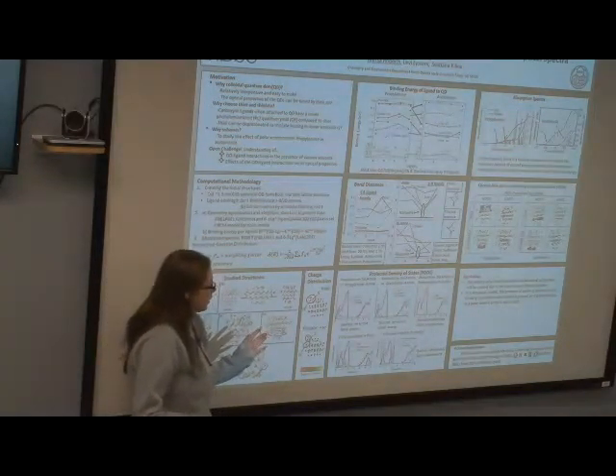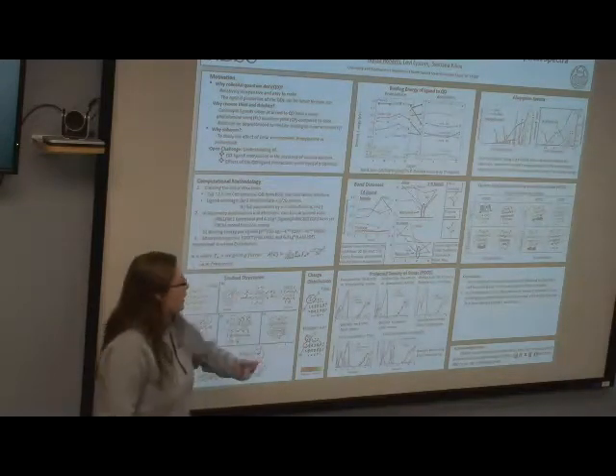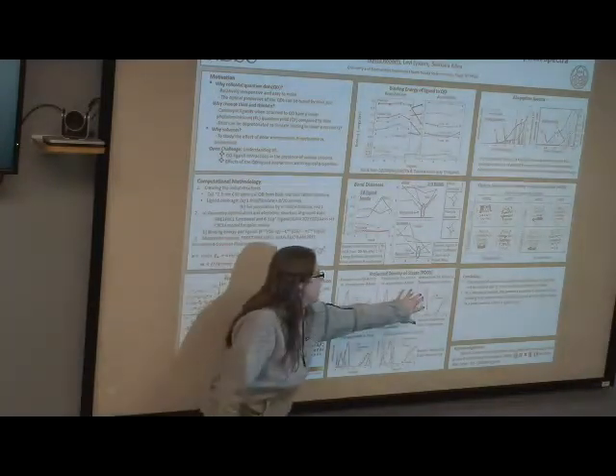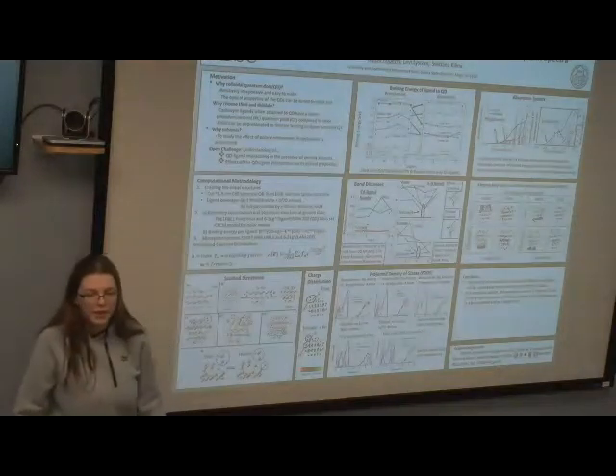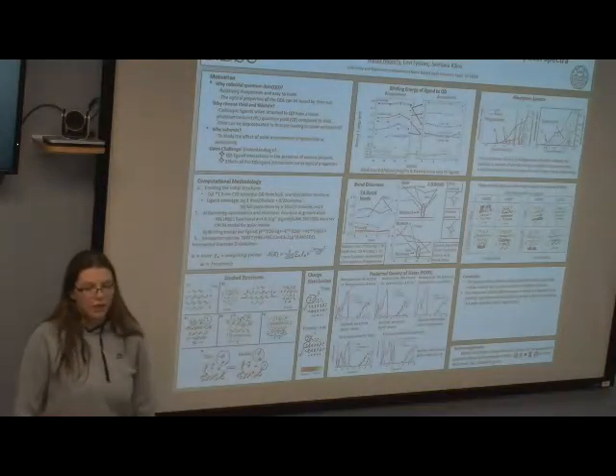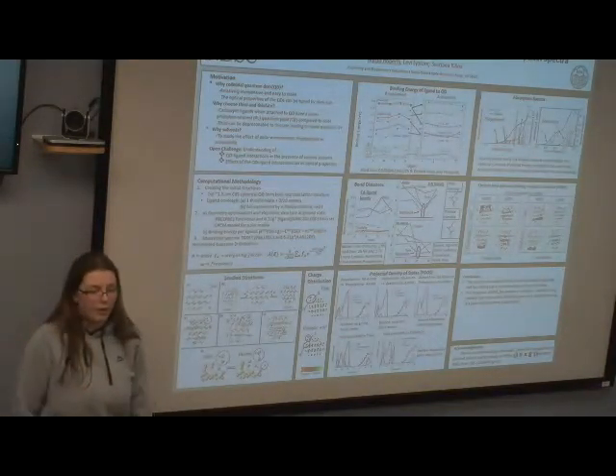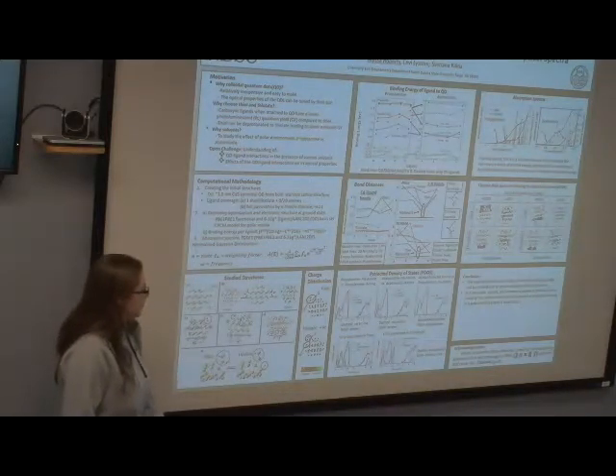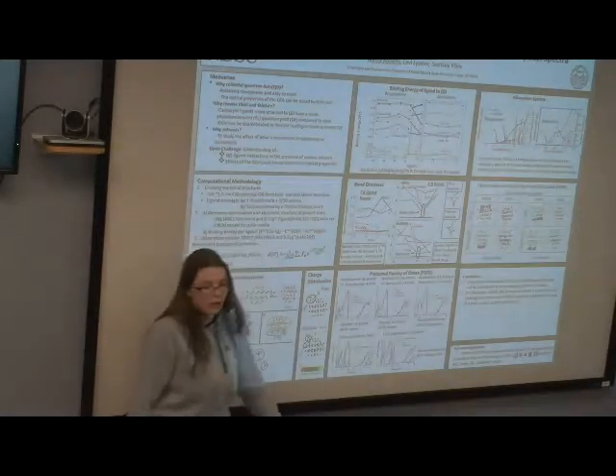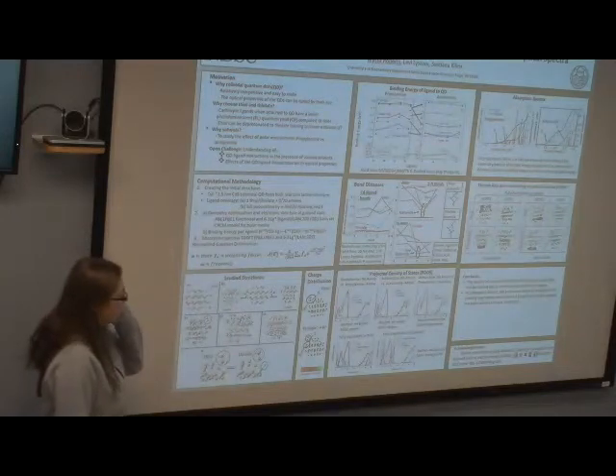What we're looking for here is a trap state, and those aren't going to occur with these three because it's only passivated by one ligand. So you're not going to have one ligand overpower the quantum dot. But this is full passivation, and we'll talk about that later where trap states come into play.